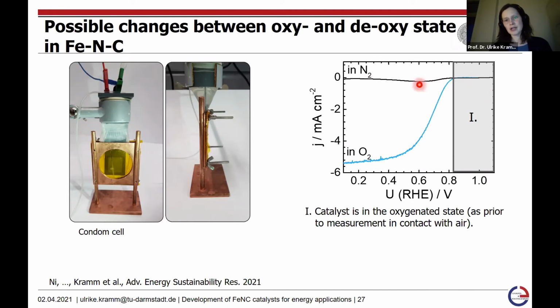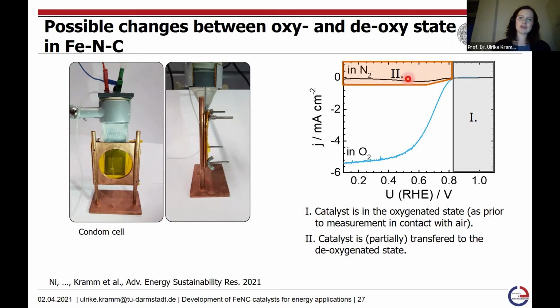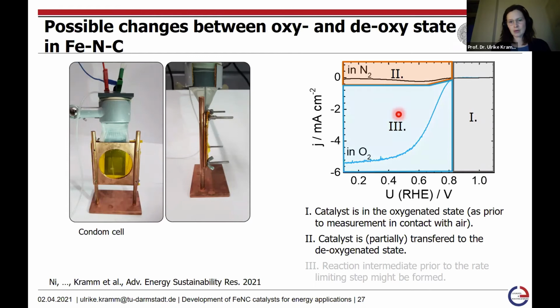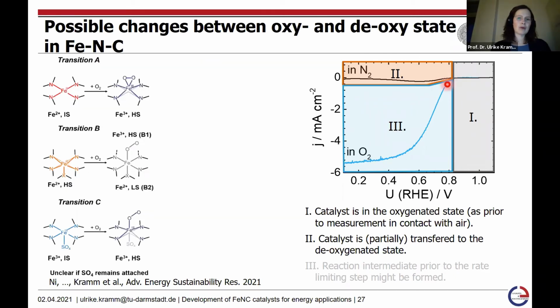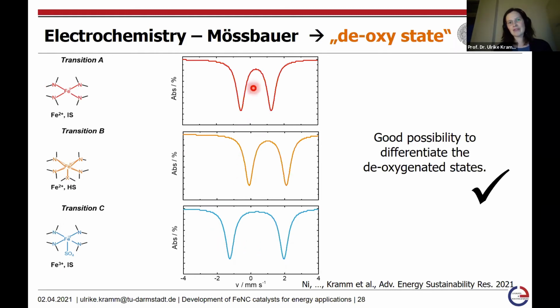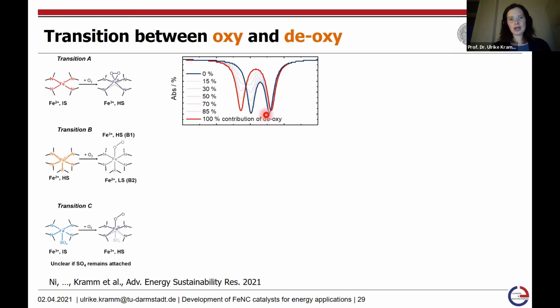When we then go below the onset potential, but keep our electrode under nitrogen, we would assume that we are able to transfer the catalyst to the deoxygenated state. And if we then even induce oxygen, of course we would measure our catalyst under operation. This is marked here in gray, as I will only focus on the comparison between the oxygenated and the deoxygenated state, and not go for the oxygen insertion in this case. So if we compare these two conditions with respect to our sites, we have the oxygenated versions and the deoxygenated versions. If we compare how the Mössbauer signatures of these deoxygenated versions would look, you can see that we now have the chance to discriminate which sites seem to be present within the catalyst material. They have quite different Mössbauer parameters in terms of isomer shift or quadrupole splitting, and based on that we can distinguish them clearly. So this is a comparison between the oxygenated and the deoxygenated state.